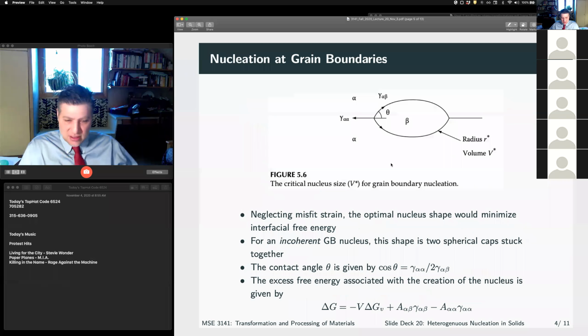Right? So let's take a look at nucleation at grain boundaries. Right? So in this case, if I've got a grain boundary here, I have a surface energy, the alpha alpha grain boundary. Right? And if I create a nucleus here, I'm going to be removing some area of alpha alpha and replacing it with some larger area of alpha beta, right? This is going to be preferred if the surface energy of alpha beta is lower than alpha alpha by essentially whatever this ratio of the areas is going to be, right?